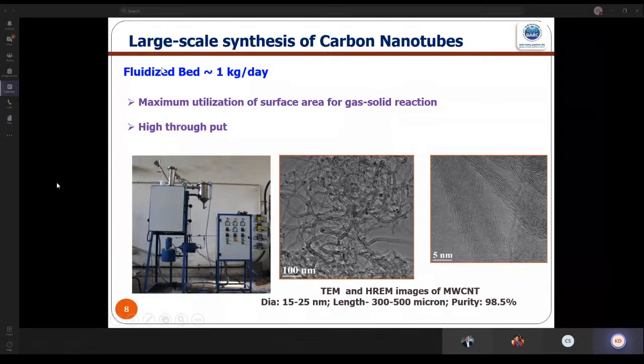We have employed a method called fluidized bed chemical vapor deposition, and at BARC we have developed a facility. We have designed and fabricated a furnace which can produce carbon nanotubes at almost a kg per day - the highest capacity in India at which carbon nanotubes are produced.